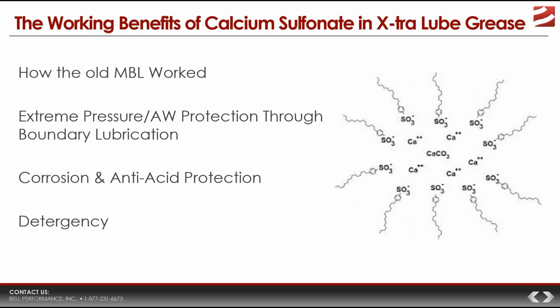We have to explain that the new calcium sulfonate in the new X-tra Lube Grease works a little bit differently. The calcium sulfonate particles in the new grease, when you expose them to the heat and pressure of a lubrication environment, don't fill in the wear. They actually form a layer of protection across the surface of the metal, and that is known within oil chemistry, or tribology, as boundary lubrication. Boundary lubrication then ends up strengthening the oil film itself, and you end up with superior EP protection.